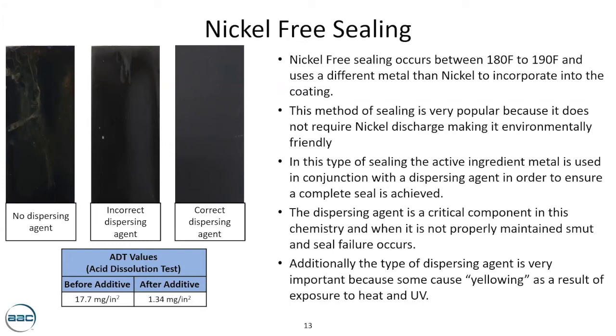And when it does work, are there any risks of it having some sort of optical degradation in the field? One of the things that I always tell customers to look at when they're dealing with nickel-free sealing is, when they're using a nickel-free seal, does the seal bath get cloudy over time? Does it get milky? If those types of things are happening, your surfactant may not be the correct one. And in fact, you may be creating more problems as it relates to smut because of that milkiness or cloudiness in the seal getting onto your parts.